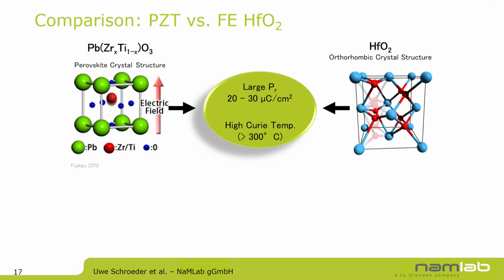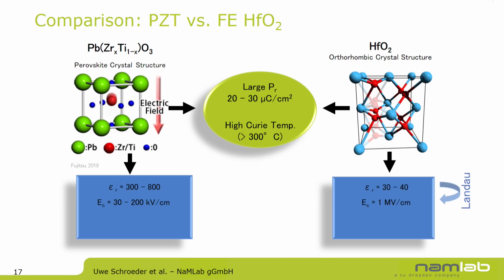They have a high Curie temperature. What you need for the material, if you want to use this in a memory application, of course, is good retention at room temperature. And now to the differences of both. They have about a factor of 10 different dielectric constant. And with this dielectric constant, you would expect, just from the Landau theory, that the coercive field of the material is about a factor of 10 different. And that's what you can see here. So here we're in the order of 300 to 800 versus 30 to 40 for the dielectric constant, and accordingly